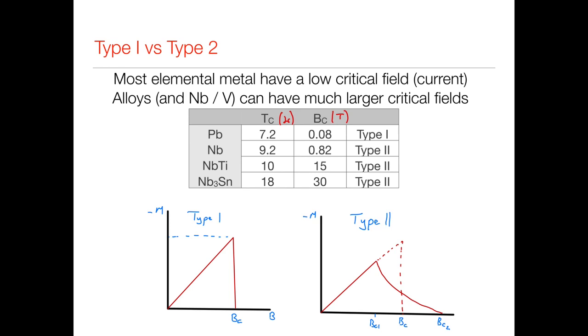What happens? Well, interestingly, the transition temperature doesn't really change. Titanium doesn't have a very high superconducting transition temperature, less than a Kelvin. So there's very little difference in the transition temperature, but look how much the critical field changes. A huge amount. 15 Tesla is a very large magnetic field. So there's something very different in this material. It can stay superconducting up to a much larger critical current or critical field.